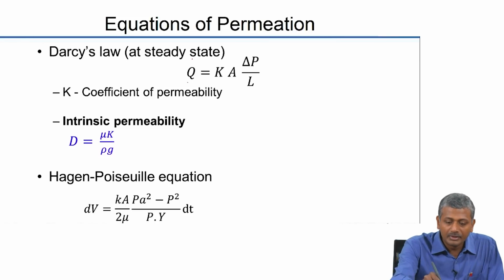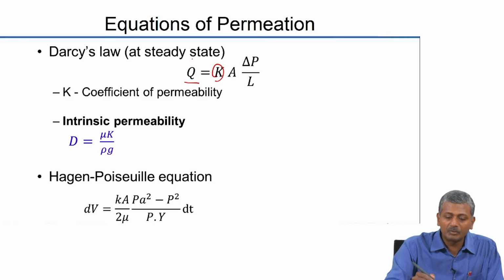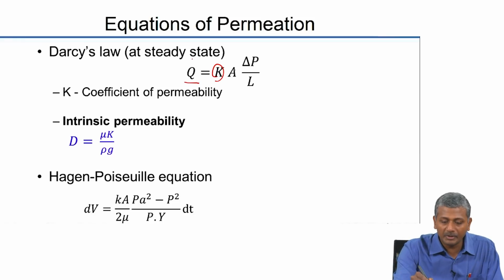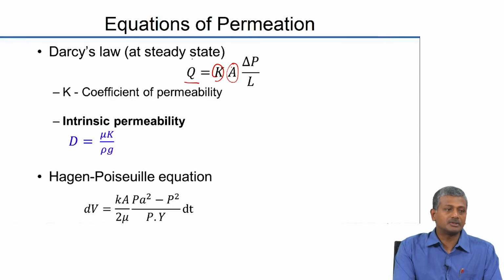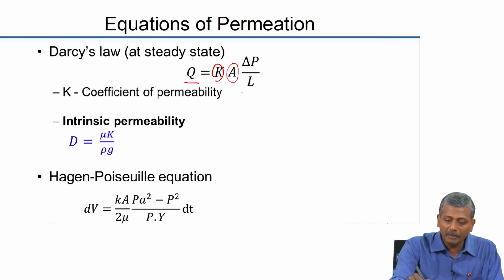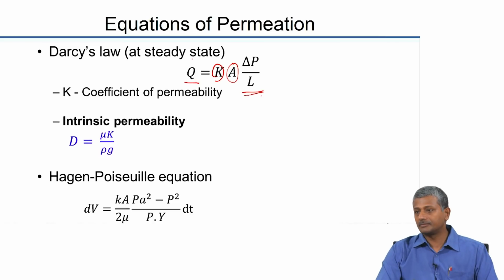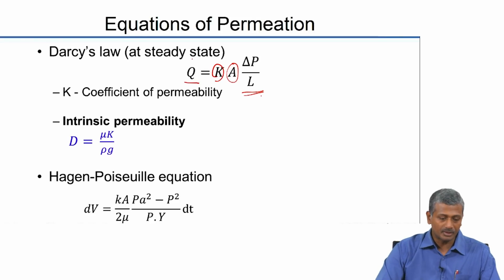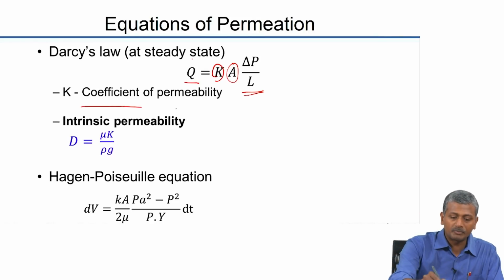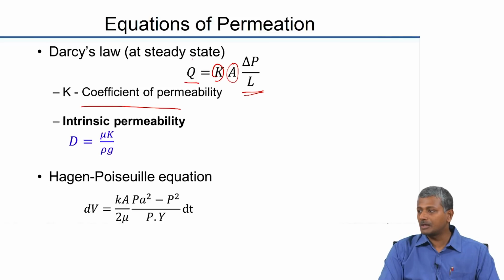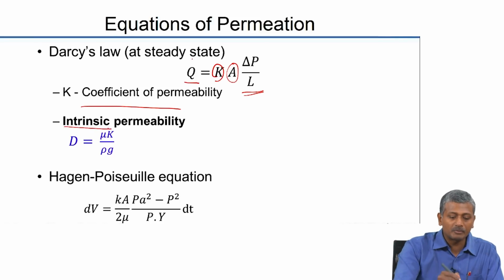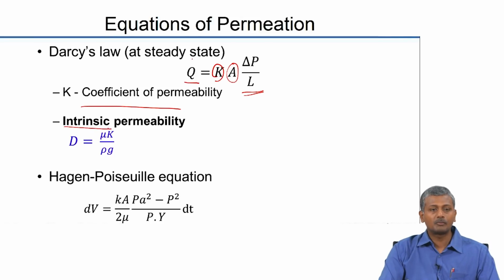So here, the flow is given in terms of the permeability coefficient K multiplied by the area of cross section across which the permeation is happening, multiplied by the pressure gradient: the difference in pressure divided by the length over which the difference exists. Okay? So this K here is called the coefficient of permeability, and oftentimes we convert this into what is known as intrinsic permeability, which is actually a material property.